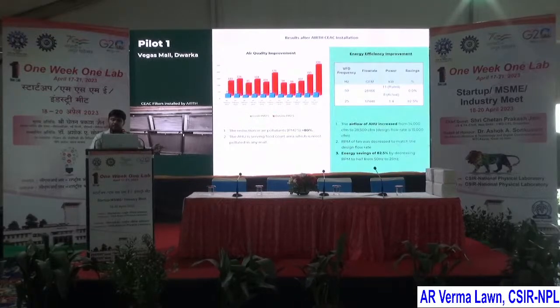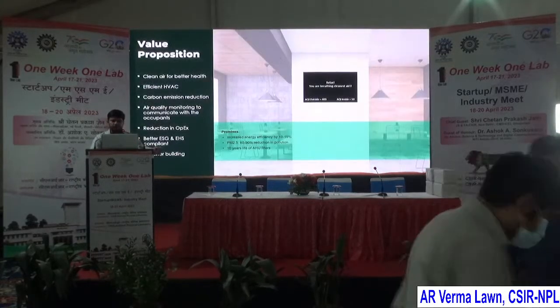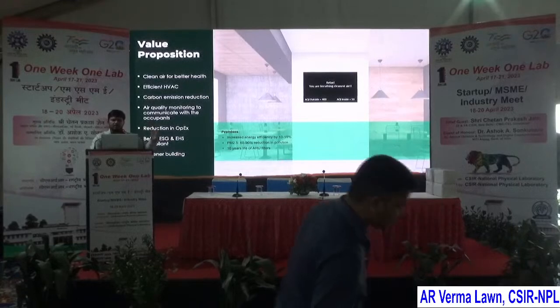Then second was energy efficiency that we were able to achieve. Around 82% of energy we were able to save here on the AHU blower. How we were able to do that is because after installation of our system, the airflow increased from 14,000 CFM to 28,500 CFM. Now to match it again to around 15,000, we decrease the frequency or we lower down the RPM, and that helped in decreasing the power. So efficiency as well.